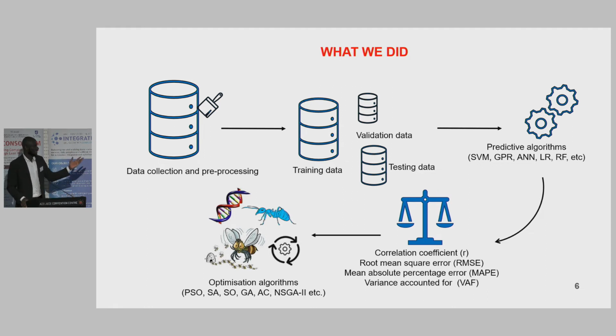And the standard metrics that we considered in this work included correlation coefficient, root mean square error, mean absolute percentage error, and variance accounted for. So for a good model, we expect the R values to be approaching 1. And in terms of the error statistics, that is the root mean square error and the mean absolute percentage error, we expect them to be as minimum as possible, approaching 0. And for the variance accounted for, we expect values as close to 100% as possible.